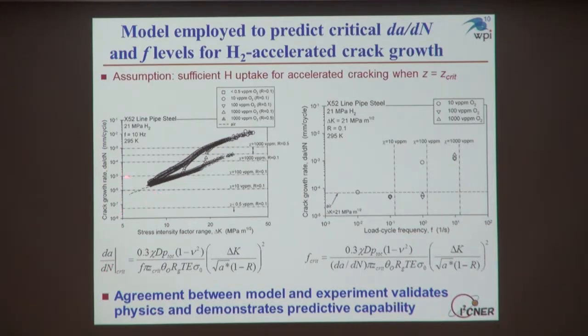So these dashed dot lines are the predictions from this model, and we're comparing where these crack growth rates start to accelerate relative to our predictions. And what we find, without me going into all the details, is that the agreement is quite good. One thing that we had to do is we can't independently determine what this critical oxygen level is. And so we used one of these sets of data, essentially to back calculate this critical level of oxygen, and then using that critical level of oxygen, we're able to make predictions for the other data sets.